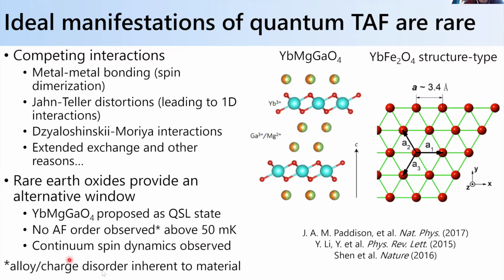But one of the open questions of this material was that the structure type it forms in is ytterbium iron 2 O4, right? And you can see that this chemical formula looks different than this one, right? The reason is that the magnesium and gallium sites sit mixed on these interstitial layers. So you have a large degree of alloy and charge disorder in the system, and it's not completely obvious whether disorder drives the underlying phase behavior, or if it's the physics inherent to a triangular lattice of ytterbium ions.